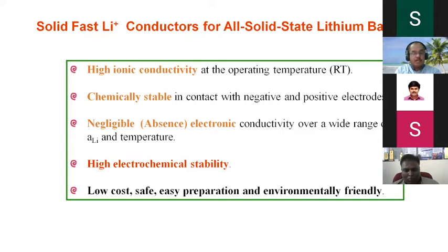So everything depends on finding a suitable solid electrolyte. If you want to realize a solid state battery, particularly with lithium metal as the anode, then you have to develop a solid electrolyte which should possess at least these characteristics. Ionic conductivity at the operating temperature, not like solid oxide fuel cells at 700 degrees Celsius. At room temperature, that solid electrolyte should possess good ionic conductivity.